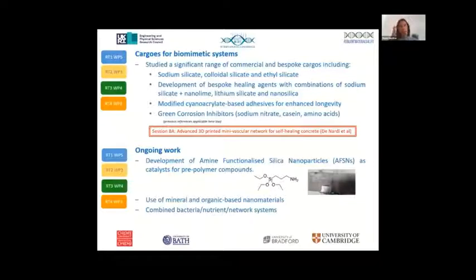Alongside that, we have our cargos. So as you can imagine, we've studied quite a wide range of cargos, those with strong healing ability, such as our cyanoacrylates, to those that combat chemical deterioration, such as the green corrosion inhibitors that Cambridge University have been looking at. We've tried and tested cargos and their ability to be encapsulated for long periods, their ability to flow, to react, to yield good bonding strength within our required timescales. And looking at modified versions of cyanoacrylates and nanosilica and nanolimes, we're really moving in the right direction in terms of getting that encapsulation and duration of encapsulation that we need.